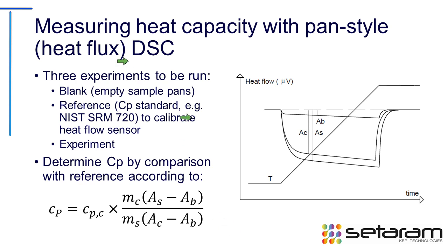So measurement of a heat capacity using a standard pan style relies on three experiments to be run. You run a blank, so just whatever your sample pan is without any sample, a reference standard, which is usually sapphire, and your experimentation. So we're running 3 experiments to measure one property, the heat capacity of the material. It's given by this formula right here.